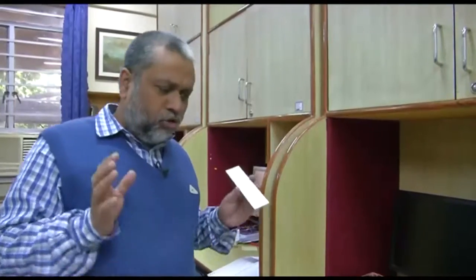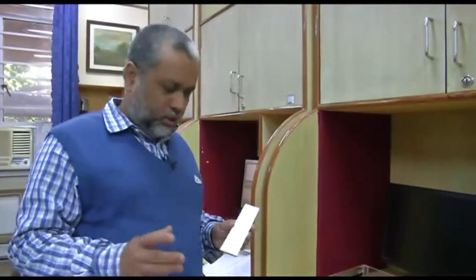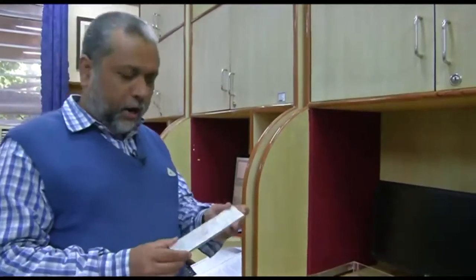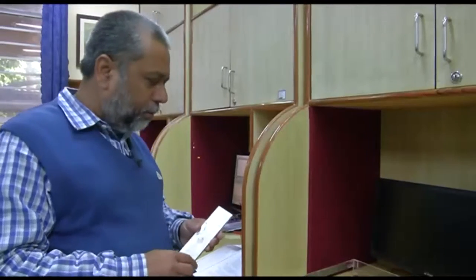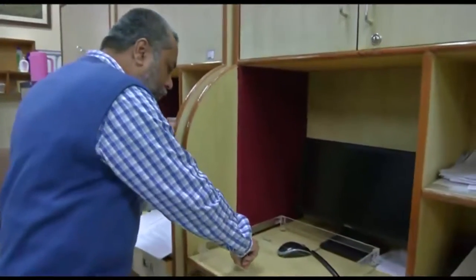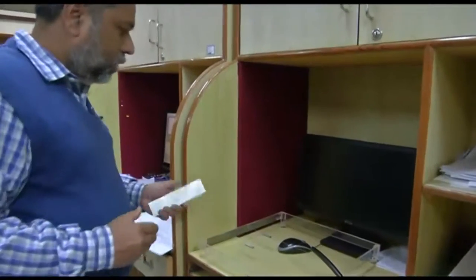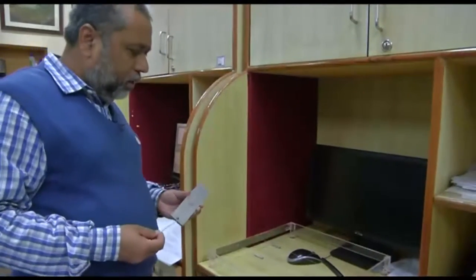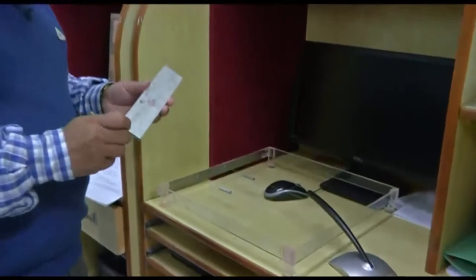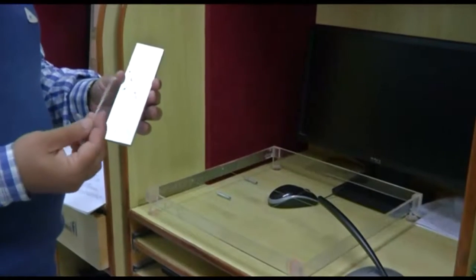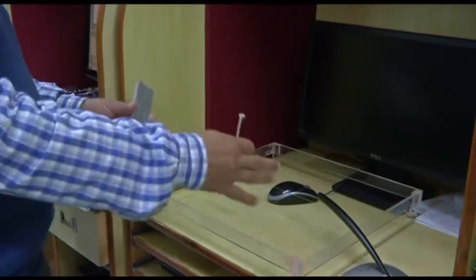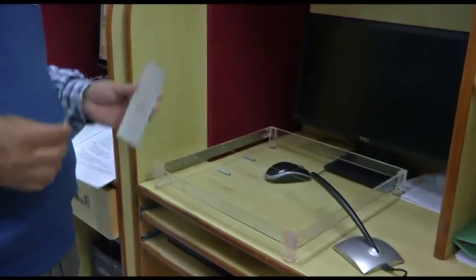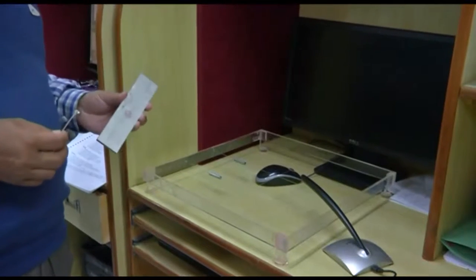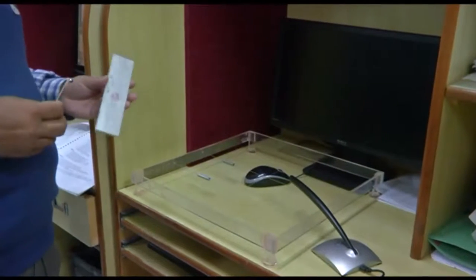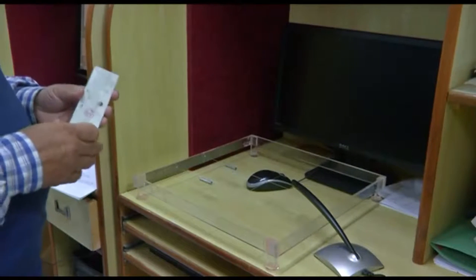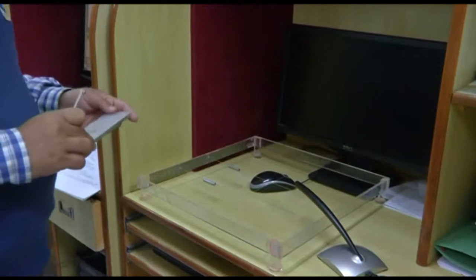Now, today I am going to show you one experiment through which we can demonstrate it. This one is an aluminium bar, as you can see, a solid aluminium bar, and we are going to put it on this particular test setup and hit it with a small impact hammer. This entire test procedure is used to find out the modulus of elasticity and the velocity of sound in a solid, and it follows a particular ASTM code known as ASTM E1876.